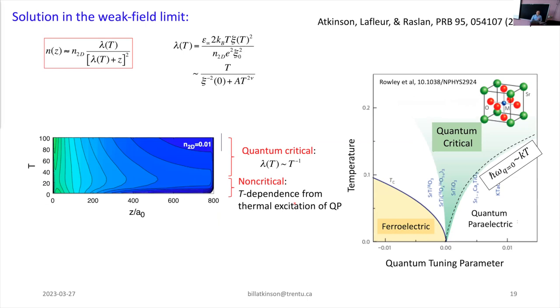And you find that you get a charge density that falls off like a power law away from the interface, which, for those of you who know about quantum criticality, is classic quantum critical behavior. There is a length scale that naturally appears, lambda here, and lambda depends on a factor of temperature and a factor of the temperature dependent correlation length. xi naught is a microscopic length scale, it doesn't matter too much. What matters from my point of view is that when you strip out everything that's not temperature dependent, you get a power of temperature in the numerator and then a power of temperature squared. Critical exponent nu is equal to 1 in this model. You get a temperature squared in the denominator.